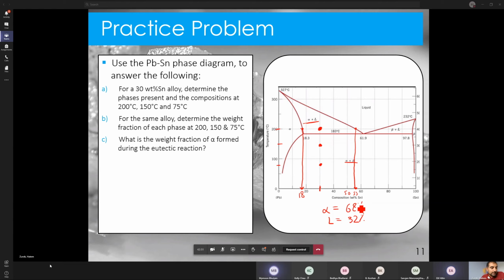Does that make sense? Do we like that? I see in the chat, yeah, 40% alpha, 60% beta. Okay, so that must be for the next one. Is that for 150? 40% alpha, 60% beta? Let's have a look. If we're doing 150, I am in the alpha plus beta region. Notice how this point is close to alpha, really far away from beta, so I'm expecting a lot of alpha and not so much beta. Remember, if I want the amount of alpha, I would take this side of the lever divided by the total. So it's actually probably even more than 60%.